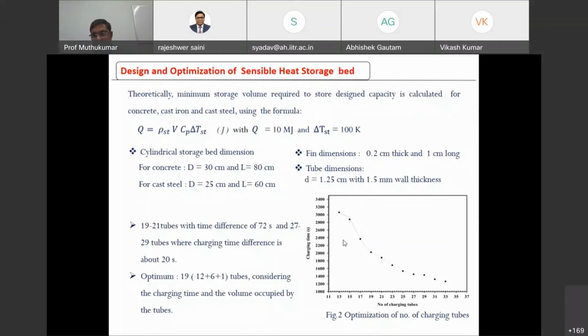This is just one example. If you increase the number of tubes, the charging time is found to decrease significantly. But you can see that between 19 to 21 tubes the slope of this curve is very low, and in another region, from 21 to 29 tubes, the slope is also low. So that means you can have the optimum either between 27 to 29 or between 19 to 21 tubes.